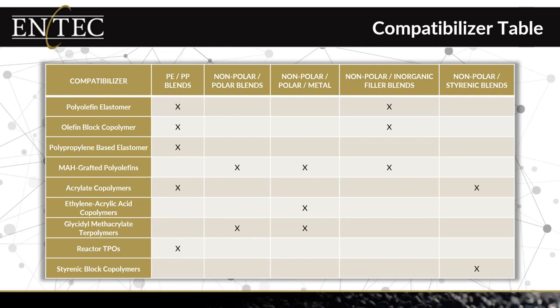And if we look at non-polar to polar polymer blends, we're going to need a reactive compatibilizer. So we're typically going to look at a maleic anhydride grafted product or a glycidyl methacrylate product if you're dealing with polyesters. And the last example I want to give on this slide is the next column where I have non-polar and polar materials and metal contamination. So in multi-layer film, it's not uncommon that one of those layers might be metallized.